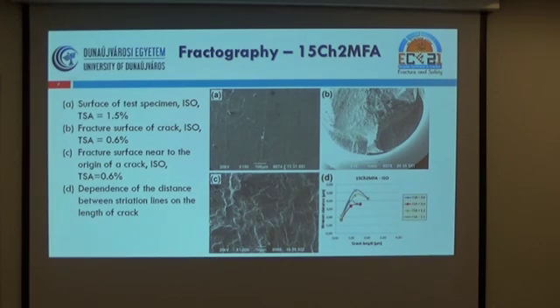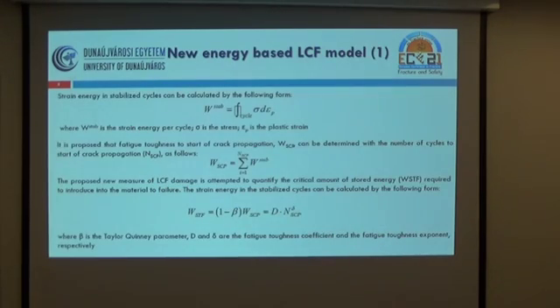And then we tried to analyze the striation lines as a consequence of the fatigue on the length of the crack, and here you can see in this small graph, and these figures are the total strain amplitude here. It was the fractography and the fatigue kinetics, and then we were dealing with the energy-based low cycle fatigue model. And the mechanical basis is as follows here.